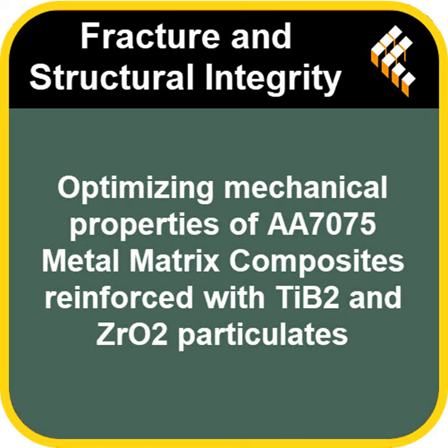And did looking at the worn surfaces afterwards give any more clues? You mentioned SEM analysis earlier. Yes, they looked closely at the worn surfaces too. The SEM images showed grooves running parallel to the sliding direction. Like tiny scratches. Exactly. This indicates a wear mechanism called two-body abrasion. It's like tiny hard points on one surface are digging into and plowing through the other.